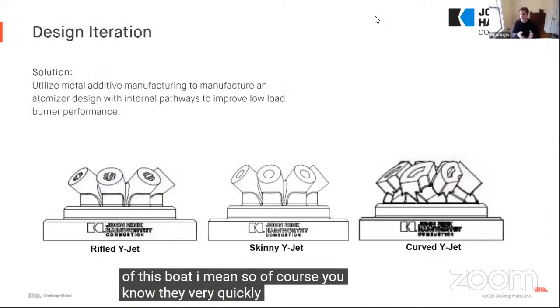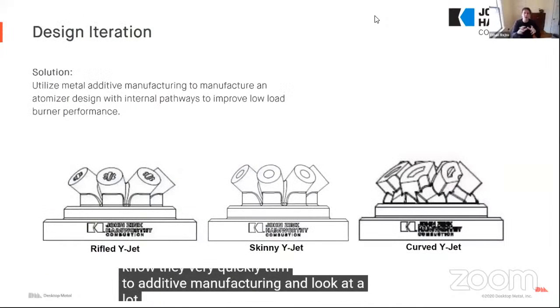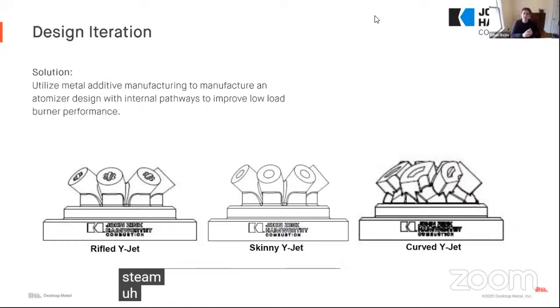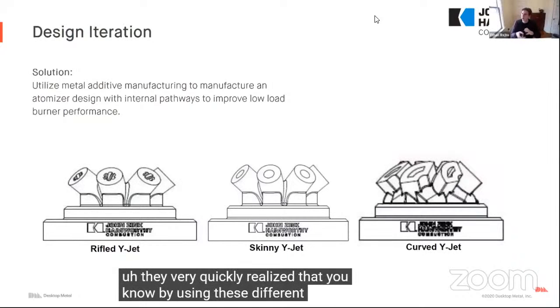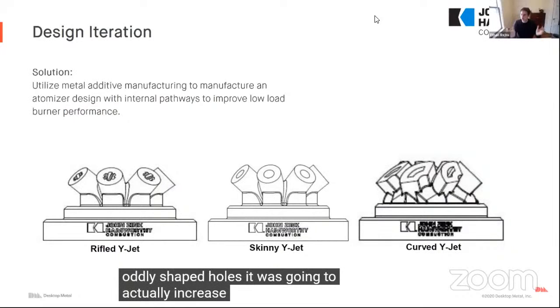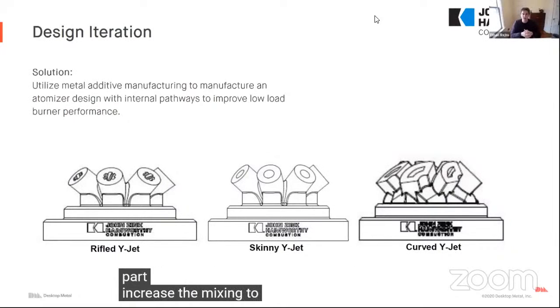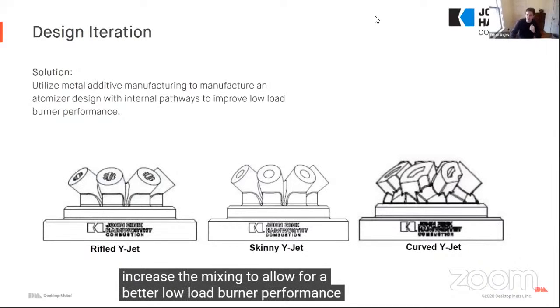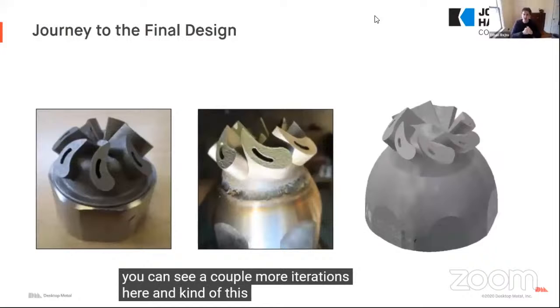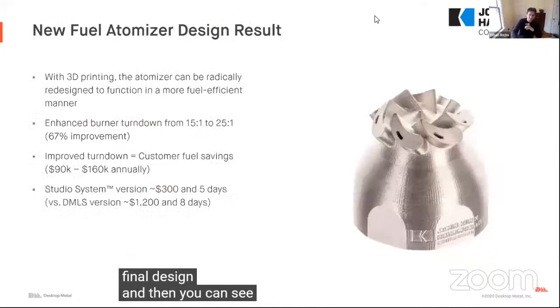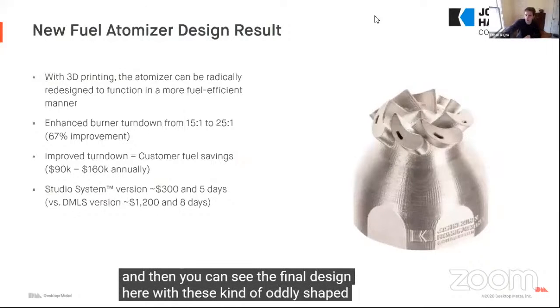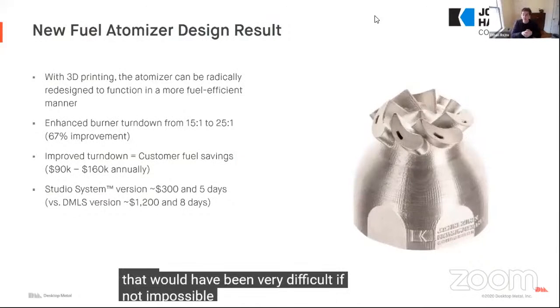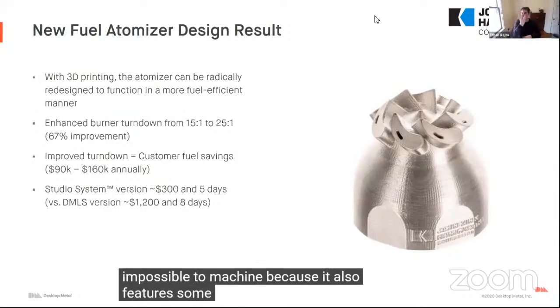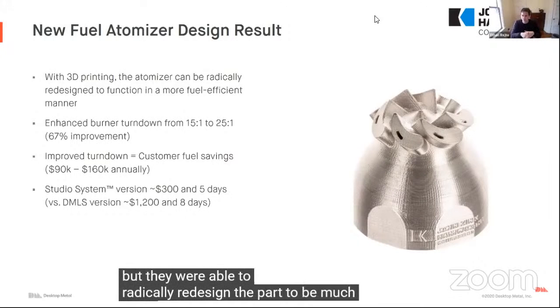So of course, they very quickly turned to additive manufacturing and looked at a lot of different designs, a lot of different geometries on how they could optimize the mixing of the fuel and steam. They very quickly realized that by using these different oddly shaped holes, it was going to actually increase the performance of the part, increase the mixing to allow for a better low load burner performance. You can see a couple more iterations here and this journey to the final design. And then you can see the final design here with these oddly shaped holes that would have been very difficult if not impossible. This part is actually impossible to machine because it also features some helical-looking channels throughout the part, but they were able to radically redesign the part to be much more fuel efficient.